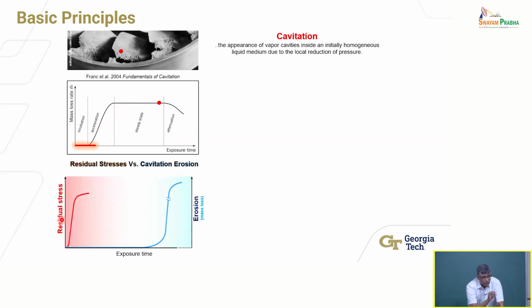Instead of using mechanical shocks, I want to use these bubbles. So if you look at this plot, mass loss versus time, initially what will happen? The shock waves will deform the surface locally, past the elastic limit, strain it, and once you remove the load, you will have some residual stress. So residual stresses will rapidly build up. If you continue to expose the same region to these collapsing bubbles, you're going to strain it more and more up to a limit, and then eventually you start causing it to fail. So that takes longer.